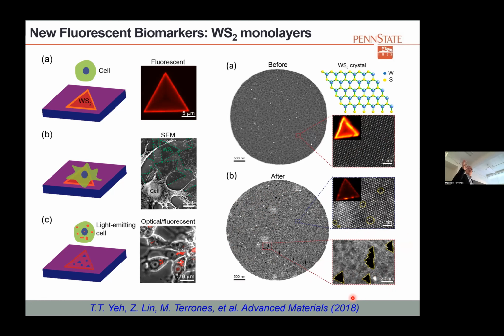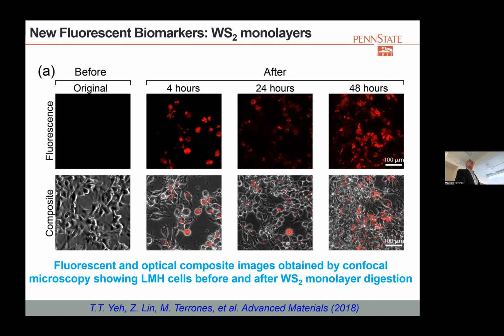What was interesting is that we tried to do cross sections of the cell, and we tried to find the fragments, but they are too small, we couldn't find them. But one of the interesting things was this experiment. Before, there are no cells, there is no fluorescence. After 4 hours, we can start seeing the fluorescence. And after 48 hours, we see the fluorescence even higher. We still don't understand why this is happening. But one thing is that the cells are dividing, so you can have second generation cells, third generation. And what was interesting is that after generations, the cells were still fluorescent.